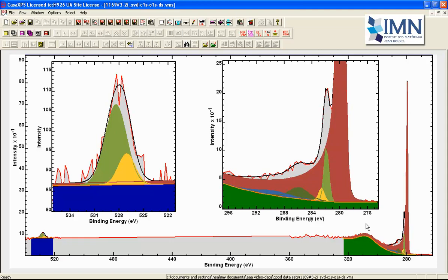However, it's clear when you look at the wider image of this model that the Doniach-Sunjic line shape forces a Tougaard background that would otherwise meet the data to be offset from the data itself. This feature of the Doniach-Sunjic line shape when you consider both of these peaks together means that you also have some contribution of the Doniach-Sunjic line shape even as far away as this oxygen-1s peak. So we have a significant energy difference between these peaks and yet we still have a contribution from a line shape that is defined using a Doniach-Sunjic.